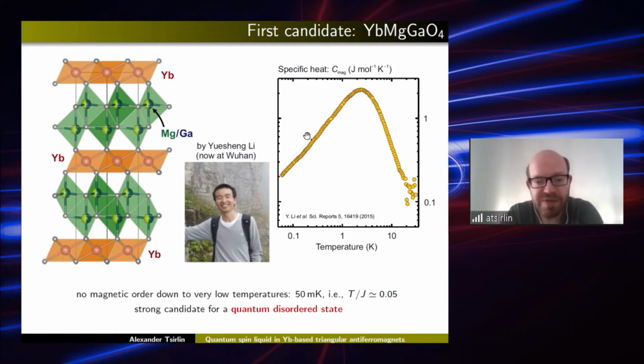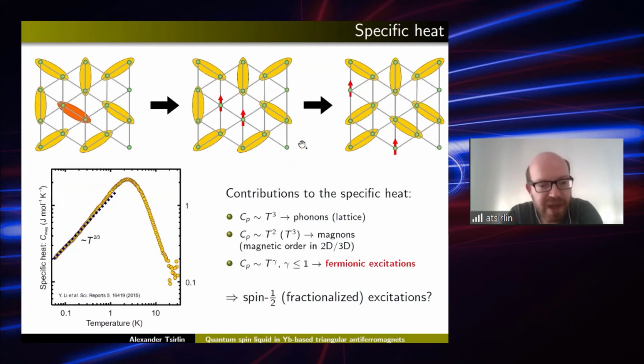And of course, we also confirmed by muSR and by other techniques that there is indeed no long-range magnetic order in this material. But as I told you before, the main draw of the spin liquid state is its unusual excitations. So we want to probe the magnetic excitations, and in fact, we can gain some insight already from the specific heat data. Because specific heat at low temperatures typically shows some kind of power law behavior.